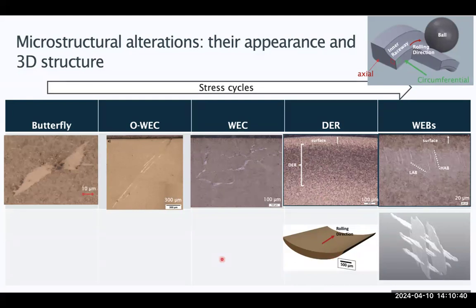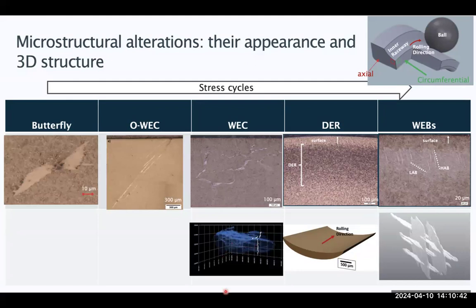The white-etching cracks in 3D look like networked cracks with white-etching area bordered. In the axial direction, again, they look very similar to the white-etching bands. They look like parallel bands, but if you look in a circumferential direction, they are like branched cracks.